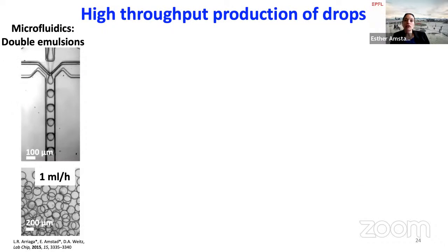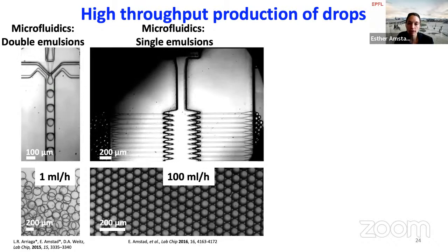A big advantage of this technology, in my view, is also that now we don't need double emulsions to make these capsules. We actually can make them from single emulsions. And the reason that I think this is a very big advantage, especially for the application we have in mind, is the throughput. If you think about the formation of these double emulsions of well-defined dimensions, we get about 1 gram of capsules per hour, which is good enough for some lab applications, but it's definitely not good enough for building macroscopic materials or even industrial applications.